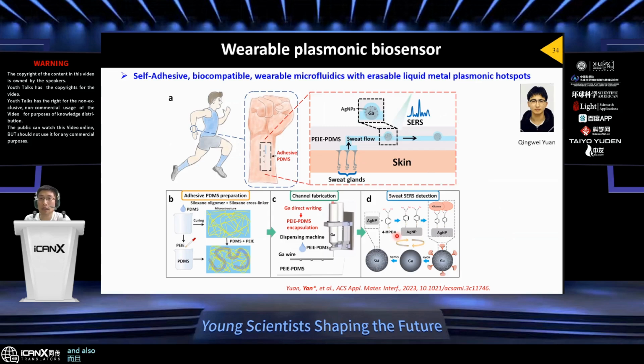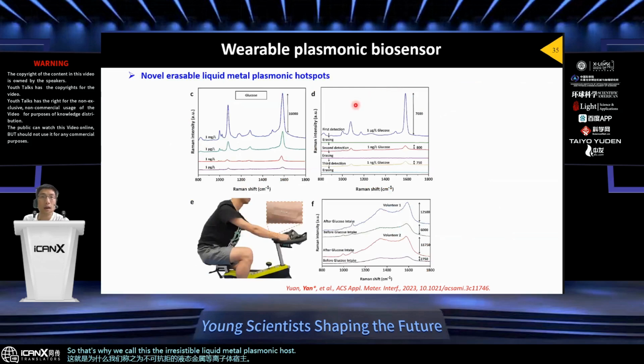And also after the SERS measurement, we can add the sodium hydroxide to remove the silver nanoparticles. So that's why we call this the erasable liquid metal plasmonic hotspots. Here you can see the limit of detection is very low. The limit of detection is about 1 nanogram per liter, and it can be used for several times.